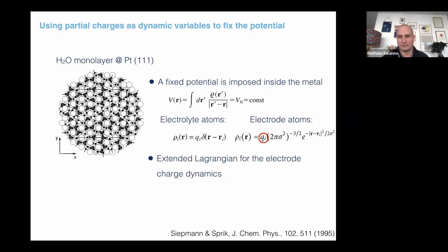And this was proposed more than a quarter of a century ago by Michiel Sprik and Ilya Siepmann, who wanted to study an AFM tip in water. So in fact the objective was to study the interface between platinum and water at the time. And the idea was that in the platinum you have a fixed potential condition, all the atoms should feel the same potential. And so they suggested to model these atoms by using Gaussian charges whose amplitude is going to fluctuate. So we go back again to a kind of charge equilibration scheme. But in that case, so you see 1995, this was a time when the Car-Parrinello method was much more used than now. And so they proposed to simulate the system using an extended Lagrangian approach.